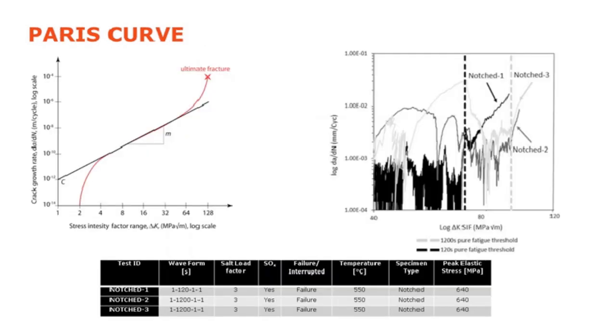So I think quite interestingly, if we start to look at corrosion and fatigue interactions on a Paris curve, we can understand a bit more about what's going on. I've included here on the left a Paris curve. If you're not familiar with it, I'll quickly run over what a Paris curve is. We've got stress intensity factor on the x-axis, measured in megapascals root metre. It's a stress geometrical parameter, and it corresponds to crack depth. So as our crack depth increases, our stress intensity factor typically increases as well.